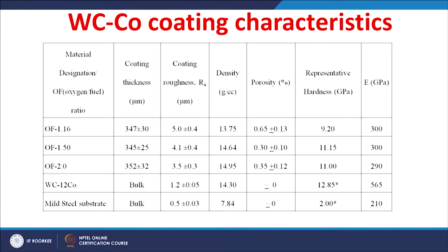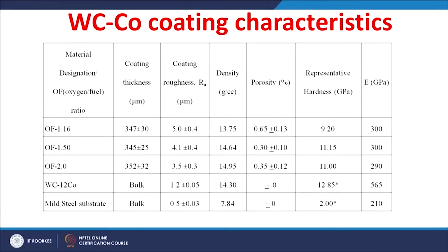If you look at this roughness variation, it is probably because of the smoothening of the tungsten carbide cuboids with the change in the oxygen to fuel ratio. Correspondingly, there is a change in the hardness and elastic modulus. For comparison, the abrasion wear was also done on the tungsten carbide 12% cobalt bulk material. Bulk material has a representative hardness of around 12.85 gigapascal and a modulus of around 565 gigapascal. So, you can see the hardness is more than the hardness of the coated surface. The mild steel substrate, on which the coating was done, was also studied for its hardness, modulus and roughness.